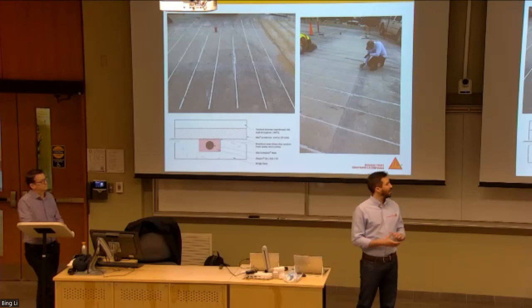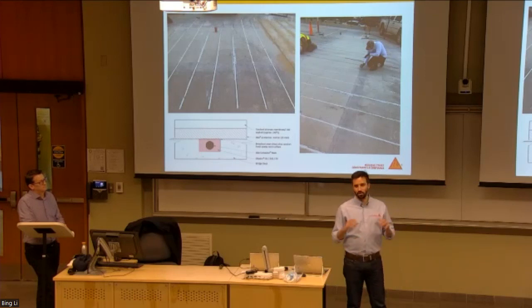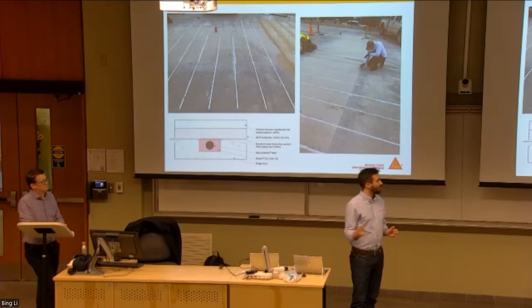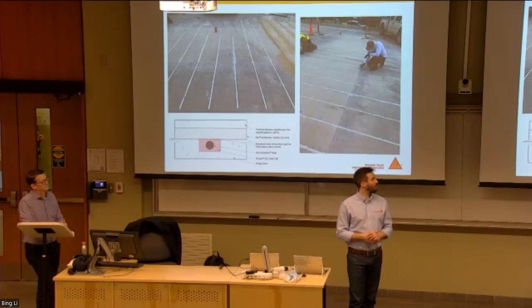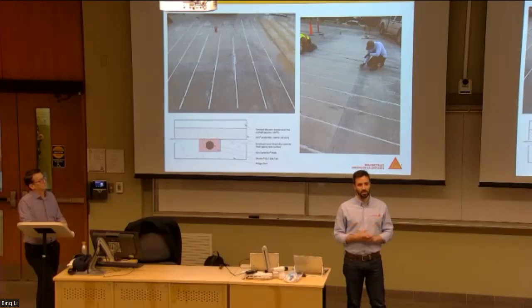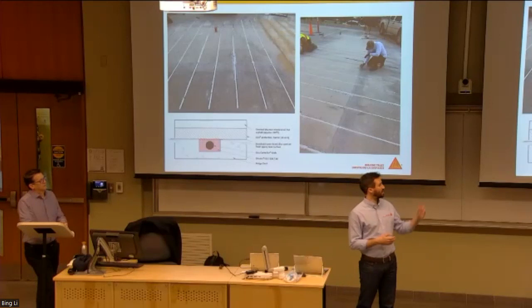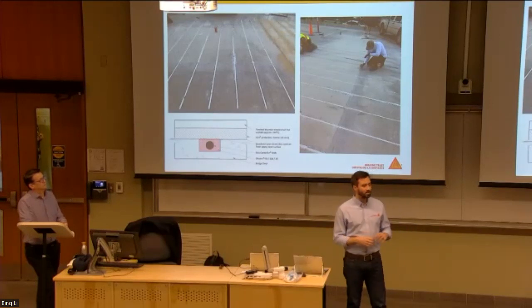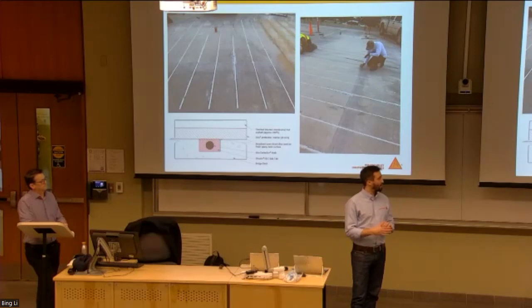They created some grooves. And the beauty with this system is you finish flush with the concrete. You don't have any difference of level at the top surface of the concrete. So you can come after and put a protection, waterproofing, anything you want. In this case, they were about to put hot asphalt on top of that. The only thing is you have to protect the epoxy that is used to fill the grooves. So that's the reason why they decided to install a Sika protective mortar on top of the groove, just 15 millimeters thick, just to protect during the application of the asphalt.